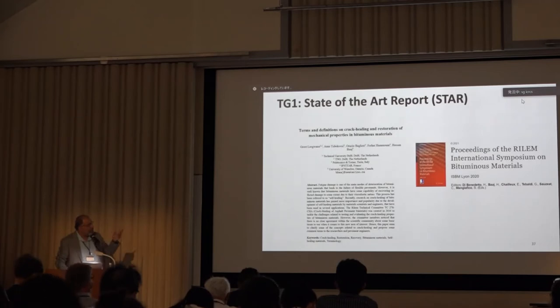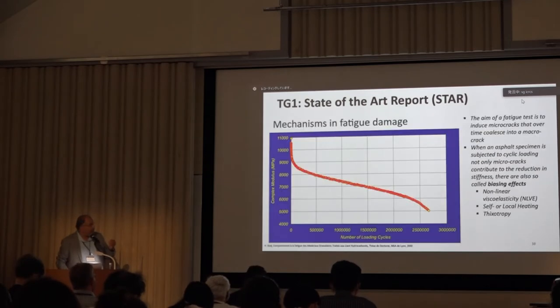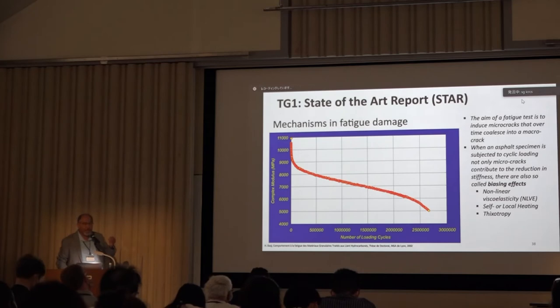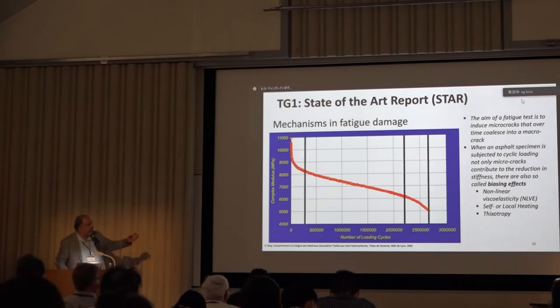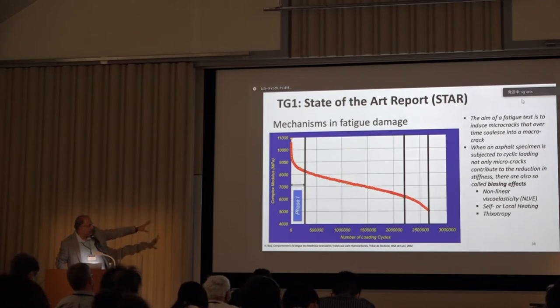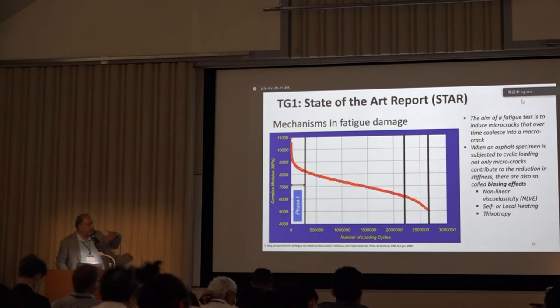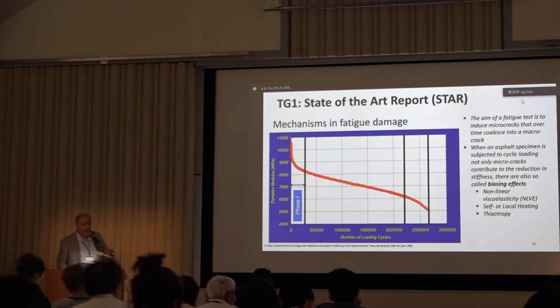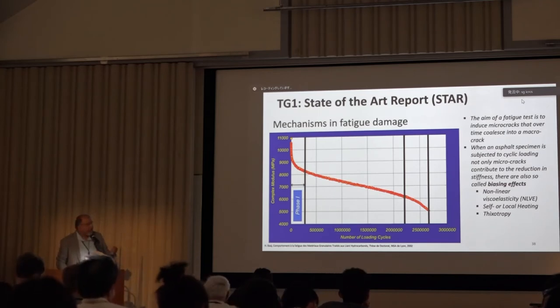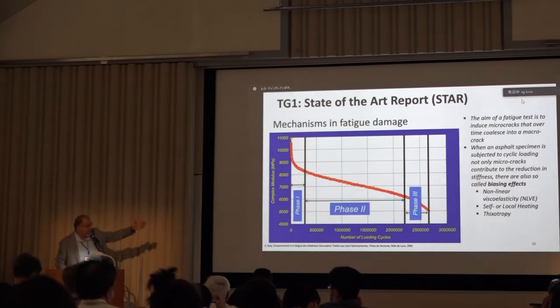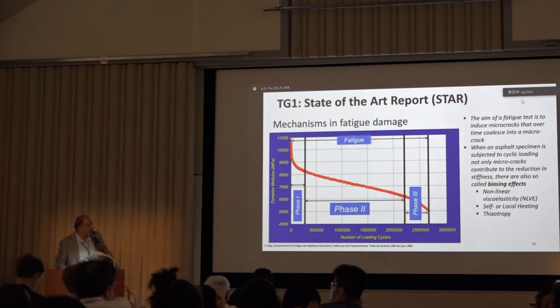In addition to the STAR, we already published an important paper on terminology and definitions. And what happens in an asphalt fatigue test is that we have 3 phases. At the beginning, the property that we're looking at, which is the modulus here, drops significantly. But does it drop because of fatigue? Actually, no. 90% of the drop, or maybe more, can be attributed to nonlinearity, to self or local heating, because the material is very sensitive to changes in temperature, and thixotropy. In the middle we have mainly fatigue, and then macro cracks appear in phase 3.